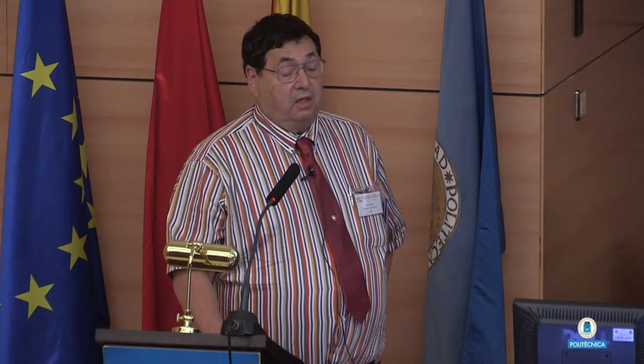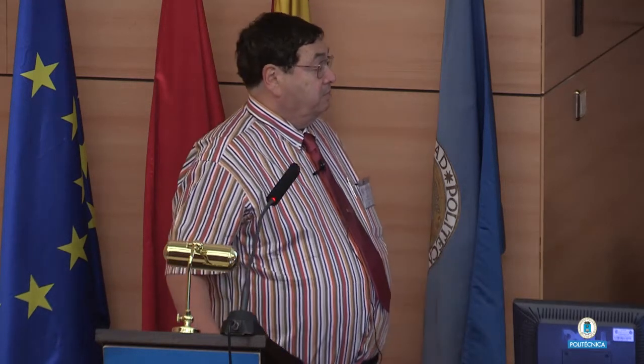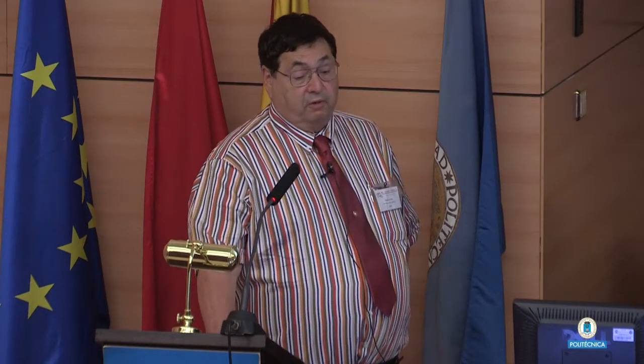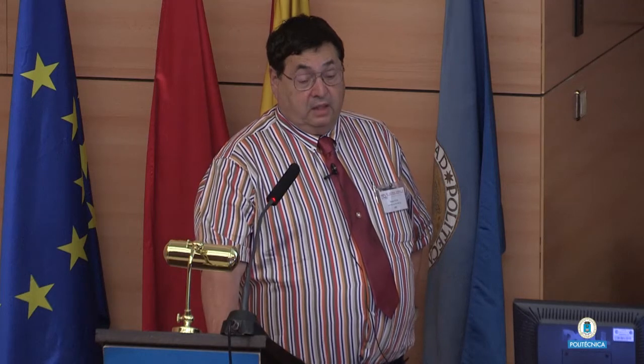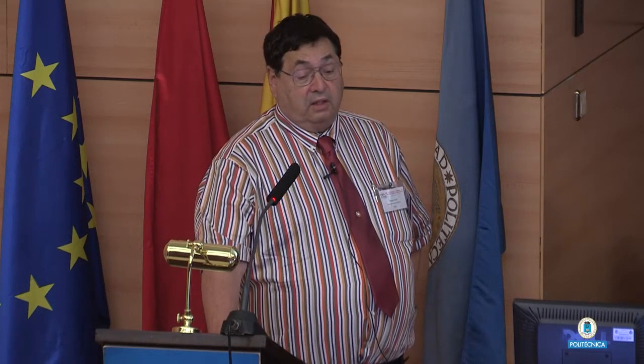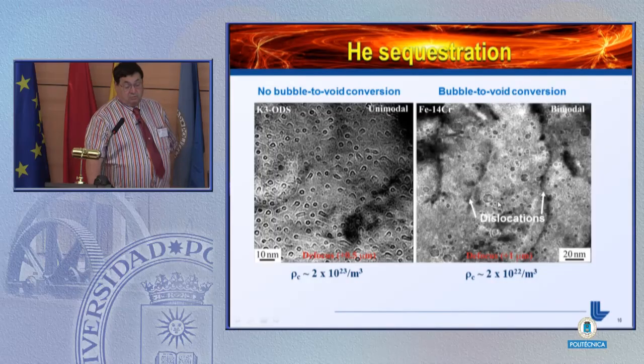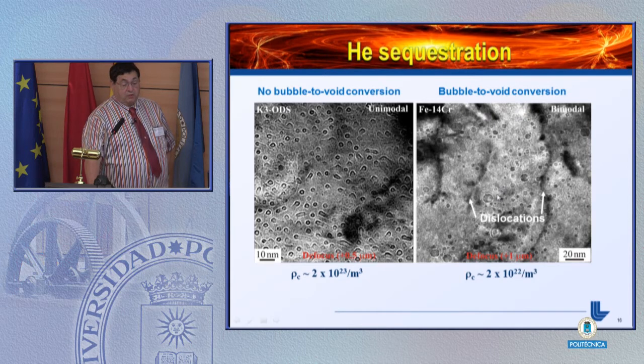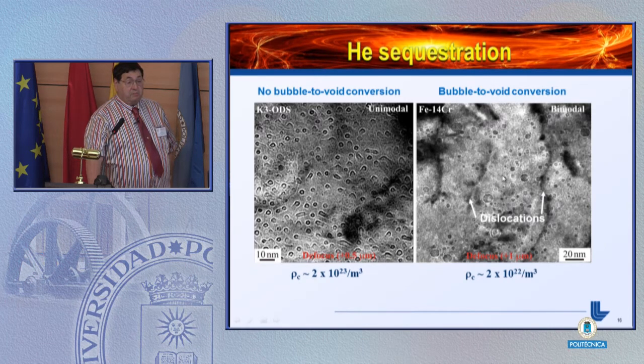Similar experiments that we've done recently on Eurofer 97, which is a good candidate material for DEMO, and would also be a candidate material for an inertial fusion energy demonstration, tell us that at 10 atomic parts per million per dpa and 20 dpa, which is a fairly significant dose if you're thinking about fission energy, but for a fusion energy machine, it's a modest dose, we already have transitioned into the rapid growth regime. And so this immediately establishes, at least as far as the ion beam experiments are concerned, a maximum dosage and therefore a maximum time that the material can be utilized before you would have unacceptable changes in the dimensionality of the materials.